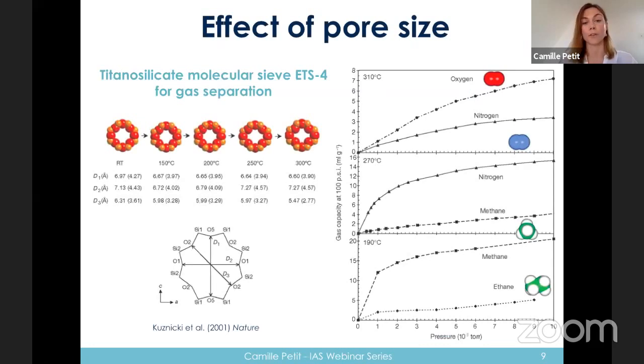If we look now at the effect of pore size, I take here the example of a titanosilicate molecular sieve, which has the particular property of changing its pore size in a way, depending on the activation temperature. So you see, as we rise the activation temperature, we have some changes in the pore size. And you look here at the distance between the silicon and oxygen atoms, and you see that we have a decrease upon increasing the temperature. And that can be helpful when you want to separate molecules that are somewhat different in size.